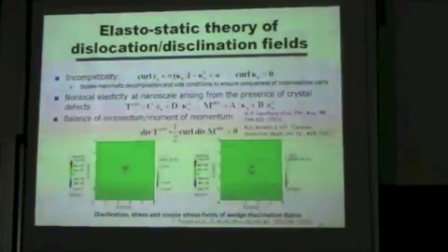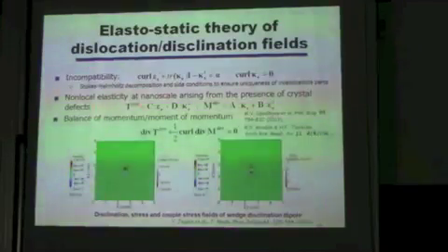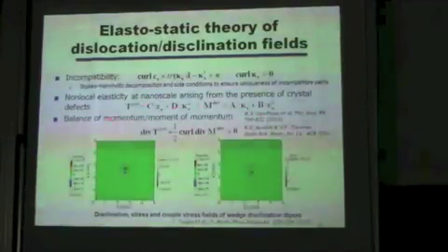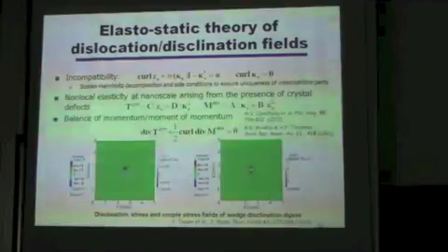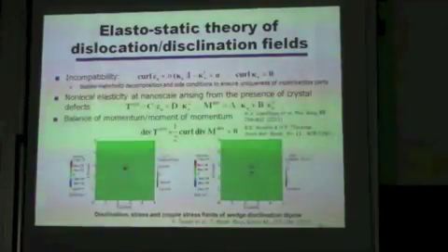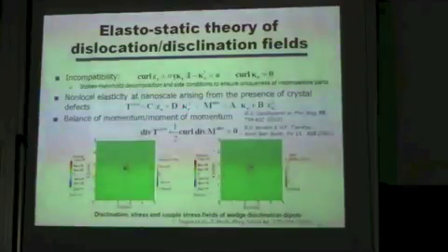Okay, now we use non-local elasticity at nanoscale, and so you can see that we use linear relations. That means that we are using a free energy which is only quadratic, and the only terms in the free energy are the elastic strain and the elastic curvature.